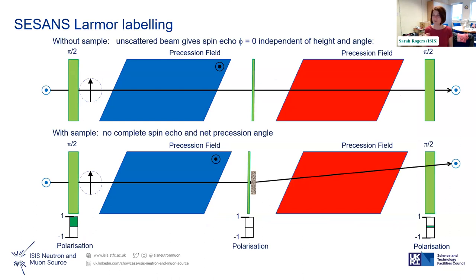As I said at the start of the talk, neutrons have a magnetic moment. You can think of them as a tiny bar magnet. So what they do in spin echo SANS is that they flip all the neutrons to be aligned. The little arrow on this diagram is a neutron. So if it goes through like this, they spin their neutron, they're all up, then it goes through a precession field. Then the green bit is where the sample would be. And then after the sample, you have an equal but opposite precession field. And so the neutron has ended up in exactly the same polarization state as it was at the start. So it's still facing up.